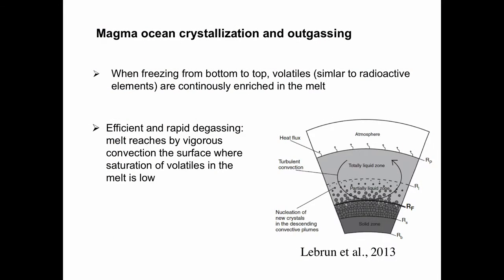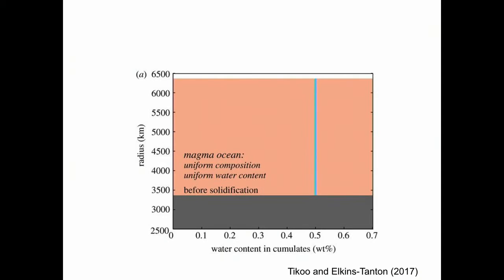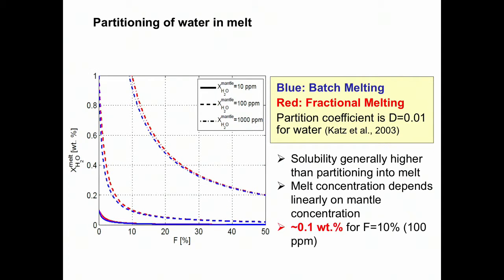Because it has a low viscosity, it's extremely strongly convecting, it cools very efficiently. And the volatiles, because they continuously enrich towards the surface, I'll come back to explain in more detail, they get released. But again, one point here: we start with a homogeneous distribution of volatiles before solidification. You start crystallizing. Then we have this partitioning of water. I don't want to explain this figure more. I think it's easier just by visualization.